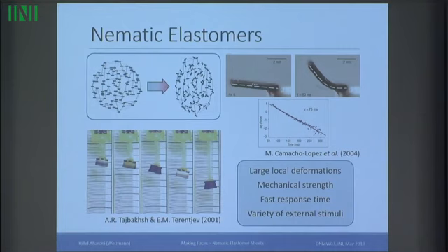And the nematic order is coupled to the mechanical deformation, and upon some actuation field, it can be temperature or light or other things, the liquid crystal tends to lose the nematic order, and the material shrinks along the director and expands in the perpendicular directions, or the other way around. And from the early 90s, people are making these materials, and even starting earlier, developing theories for them.